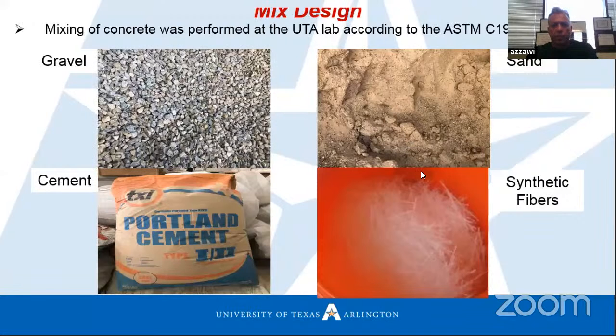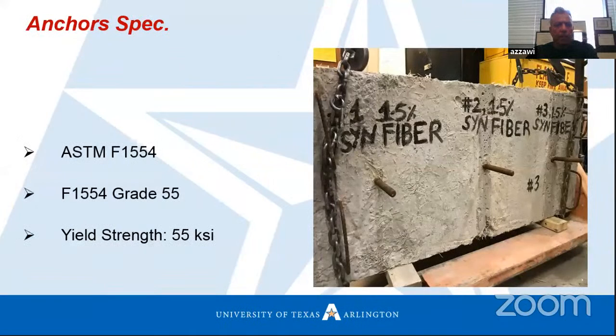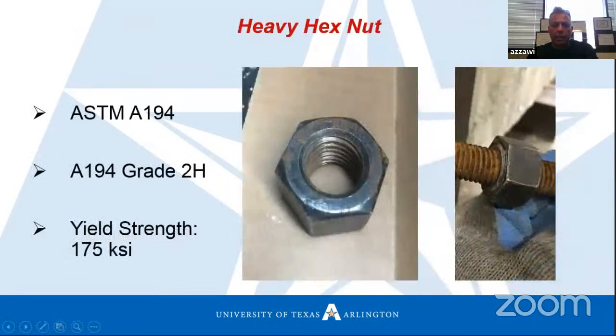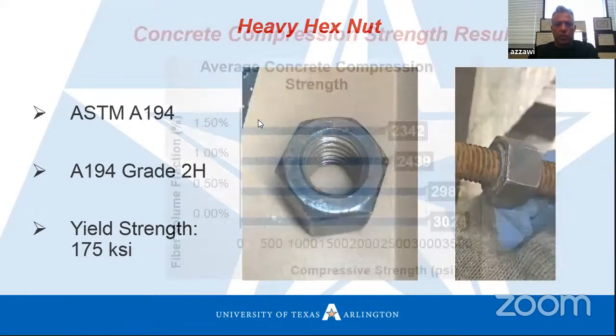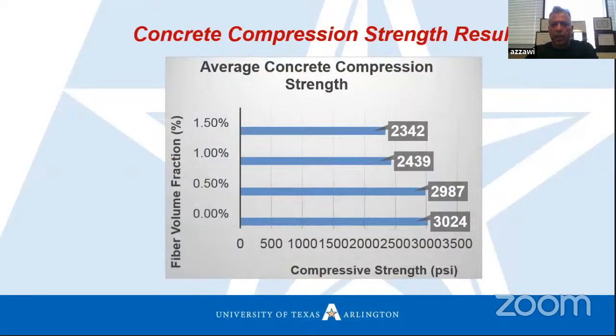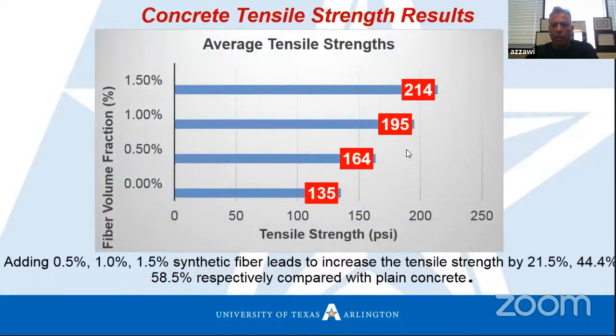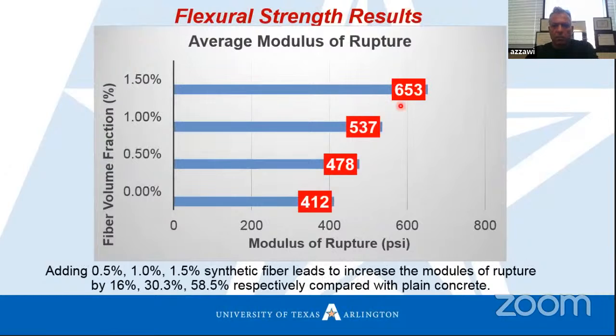Also, we have our mix design. This is the synthetic fiber we used in this study. The anchor specifications are provided. These anchors are 55 ksi yield strength. Also, we had heavy hex nuts we used during the test, and these are the specifications of these nuts. The compressive strength of the concrete is available in this slide. The tensile strength also shows an increase as the percent of fiber increases, and the modulus of rupture also increased. These are the percent increments.